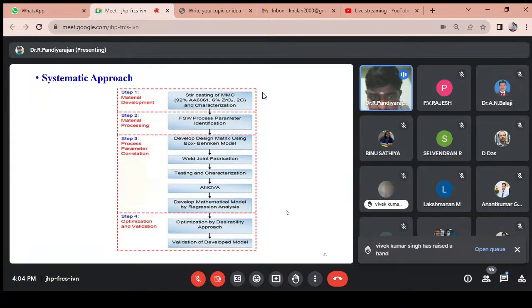Step number 3 is process parameter correlation. For process parameter correlation we choose the Box-Behnken method. It is used to develop the design matrix using a number of trials. After we develop the design matrix, we fabricate the weld joints, and testing and characterization are also done. The testing and characterization values are also input to the Box-Behnken method to develop the linear equation using ANOVA, analysis of variance, develop the mathematical equation and find the error percentage of the mathematical equations. Finally, step number 4, we have to find the optimum and the validation results. Once we find the optimum process parameters, we evaluate the results from validation methods. Again, we test 3 to 5 times and find the error percentage. This is the systematic approach